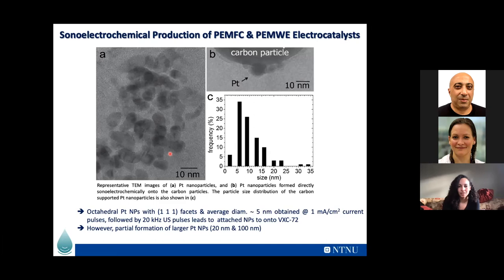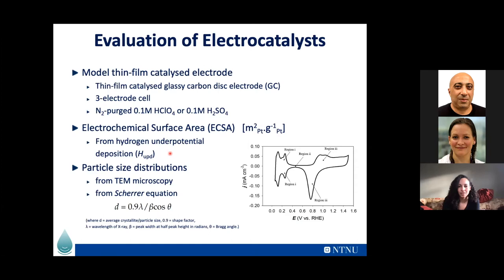Okay, there we did the usual evaluation of the electrocatalyst. This is the model thin-film catalyst electrode that everyone is using, the famous Gasteiger et al. We came up with a process of screening electrocatalysts. We look at those nanoparticles mixed again in catalyst ink, you drop cast them onto your glassy carbon electrode in a three-electrode system. That electrode is immersed in an N2-purged perchloric acid and sulfuric acid, and you do your calculation of the electrochemical surface area in that zone here, which is the hydrogen underpotential deposition.